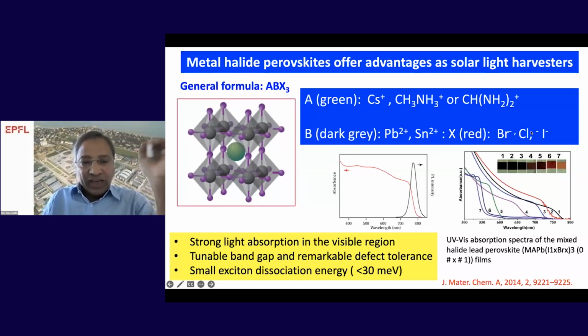So this material has unique properties. For example, when you mix lead iodide and methyl ammonium iodide in a 1:1 ratio, you form a perovskite three-dimensional structure. And this three-dimensional structure has a strong light absorption in the whole visible region, as shown in this absorption spectra of the material. So this is the absorption spectra of the three-dimensional perovskite material, which absorbs all the light within the visible region from 400 nanometers to 820 nanometers.